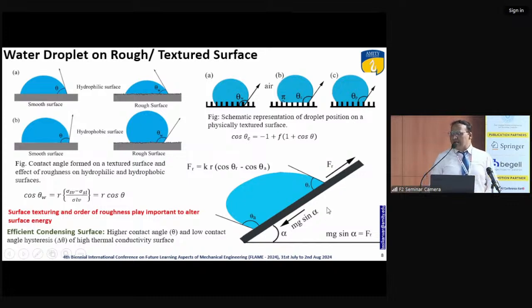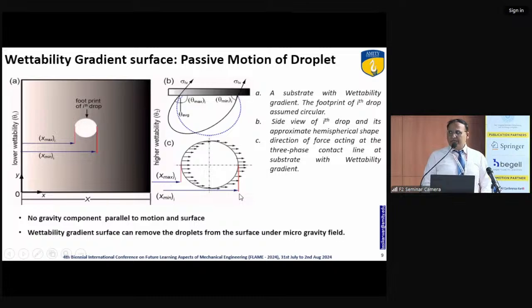A droplet slides when the retention force is overcome by the component of gravity. Generally we prepare low contact angle hysteresis, because we want to remove the drop from the surface very fast. Here I am showing what a gradient surface means. On this surface you can see lower wettability here and higher wettability there. If a drop is here, because of a passive force the drop slides from lower wettability to higher wettability automatically, passively. This type of surface is called a wettability gradient surface, and it has passive motion of the droplet by nature, so it is a kind of self-cleaning.